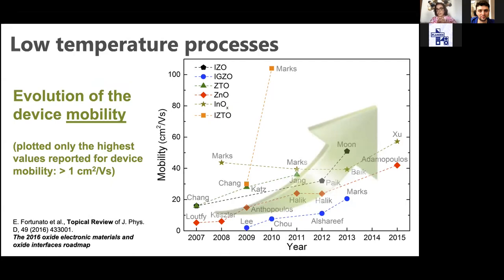The electrical mobility is not a golden figure, but it is a figure of merit for these devices. And what we are always looking for is a high mobility, which means that we are looking for a high speed. And besides decreasing the temperature, we observe an increase in the electrical mobility, since even from the chemistry side, we know more deeply about all these reaction processes. Also, we are using not only temperature, but other sources of energy, like laser and so on. And it is possible to have nowadays thin film transistors, in some cases with superior electrical performance than the same devices done by a physical technique like sputtering, for example.